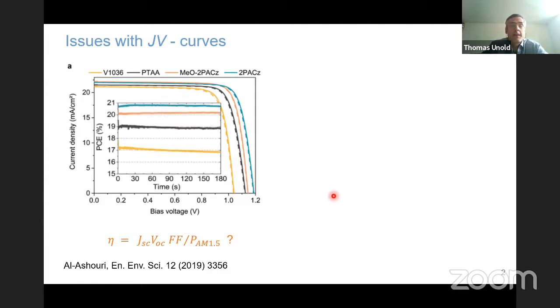Then of course, in perovskite, it's very prominent. You should really check for stability because sometimes you have high efficiencies and they last only for some seconds. And then if you report that, it's also nice to do it with absolute efficiencies, not normalized efficiencies. Sometimes people do it with normalized efficiencies, but then it may happen that the device with 21% actually crosses the one with 17% after 60 seconds. That's also not so useful.